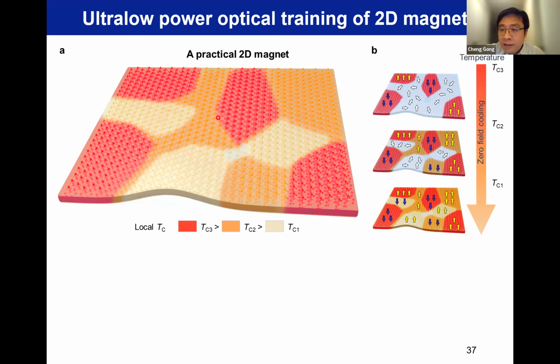Given they are decoupled by the non-magnetic phase in between them, they can get into the ferromagnetic phase randomly. Of course, if they are close to each other, they probably can feel a little bit of stray field. But stray field, as a dipolar interaction, will actually push them into an antiferromagnetic, anti-aligned spin configuration. So you will have the formation of multiple domains. It's not simply the ideal case. You consider the competition between exchange interaction, anisotropy, and dipolar interaction. But practically, you have different patches, so you get multiple domains because they are weakly or even not interacting with each other. That's why you can form multiple magnetic domains.